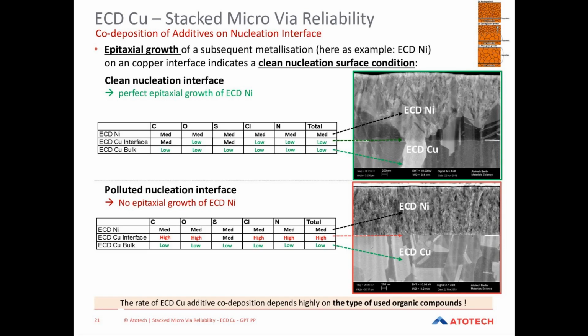What does it indicate now? If you see that this crystallization from one metal layer to the next metal layer gets continued, then you can expect a very good bond between the two metal deposits. So epitaxial growth of metal structures indicates a very clean interface. Nothing disturbed the continuation of the metal growth in the next layer. And on purpose, we show you here copper and nickel plating to show you that even different metals can have a very good bond by epitaxial growth.